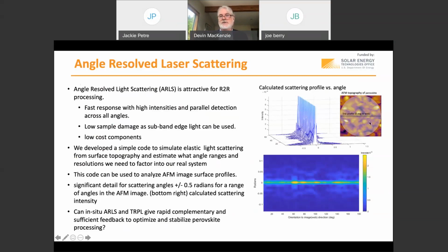And so we developed this to take line profiles out of an AFM image, or really any image. We use AFM topography images and then actually do scattering profiles, and you can rotate that. You can sweep. You can take line profiles anywhere in the image. We thought it was quite interesting to sweep the line profiles in rotation to look for texturing. Do we see things in the linear direction of the coating or orthogonal to the direction of the coating? So that's how we developed the code.